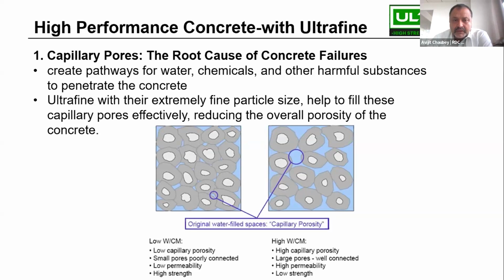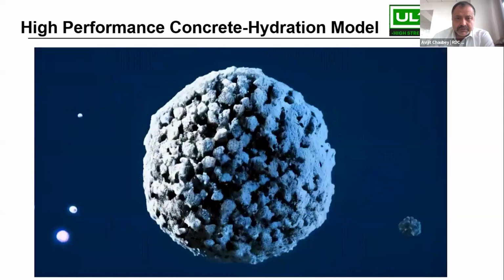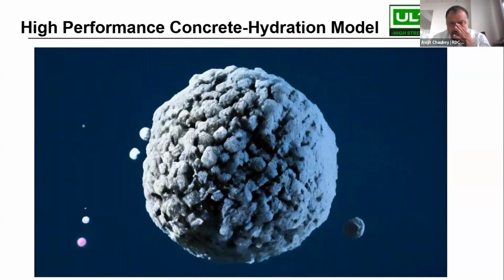Now, what happens with ultrafine minerals is that they are able to go inside the pores. They are able to block these big pores, which are called capillary pores, and also hydrate. These are nothing but fly ash or GGBFS or microsilica particles, and they lead to better hydration of cement, a faster reaction, and much higher strength as compared to just the cement. So you are able to get the same strength at a higher water cement ratio and a better workability.